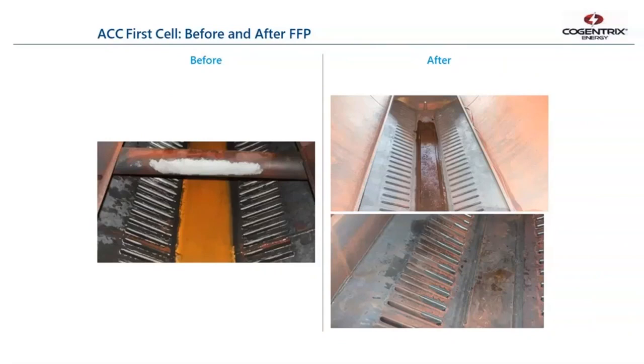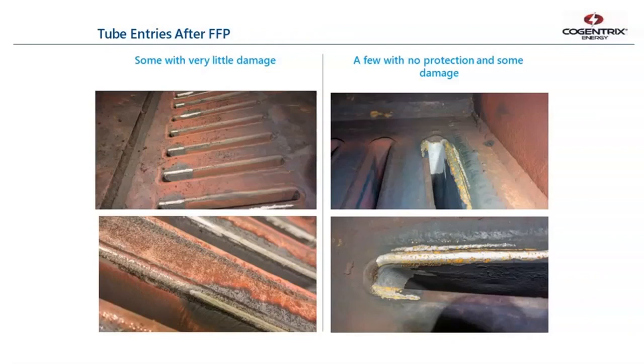You can see everything is a little bit hydrophobic. It's not completely covered up in red, but there's no flash rust. And you can see in the worst spots there is still a little bit of two-phase FAC right at the tube entries. Here's some more. These are all after pictures. Zoomed in, you can see hydrophobic surface left.